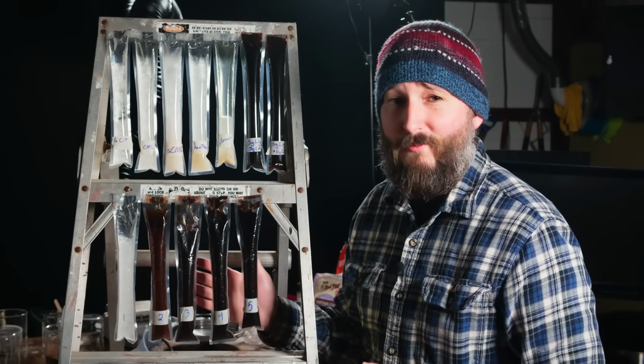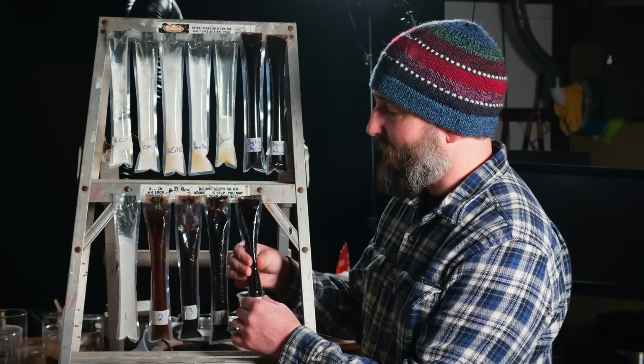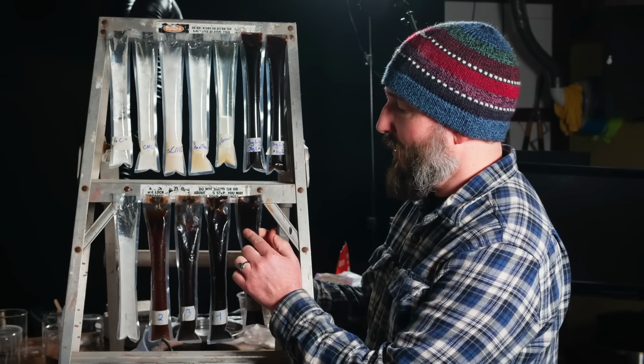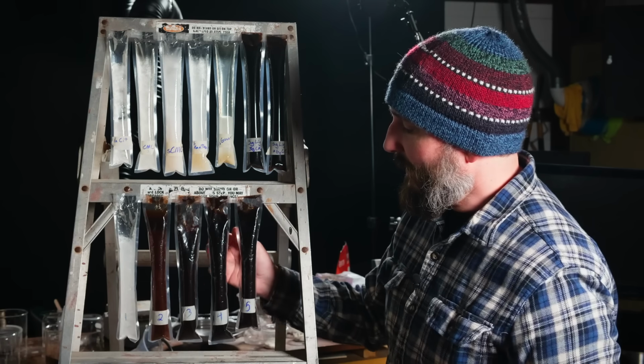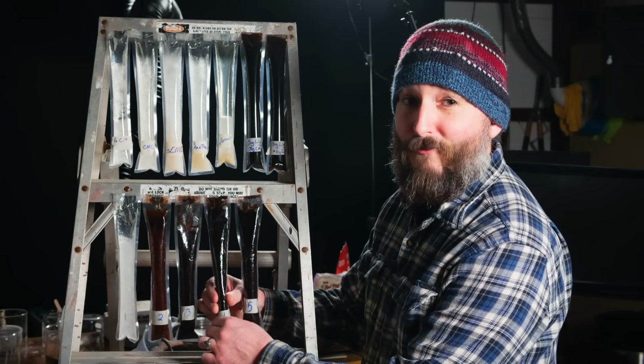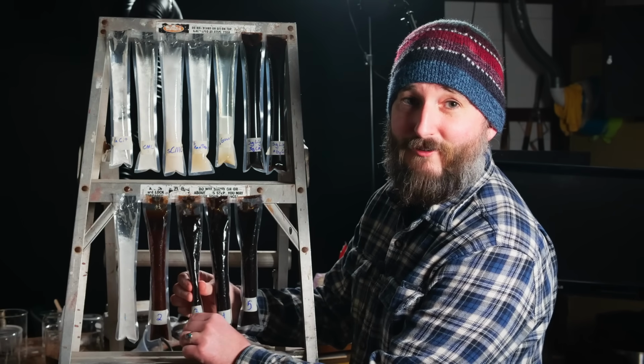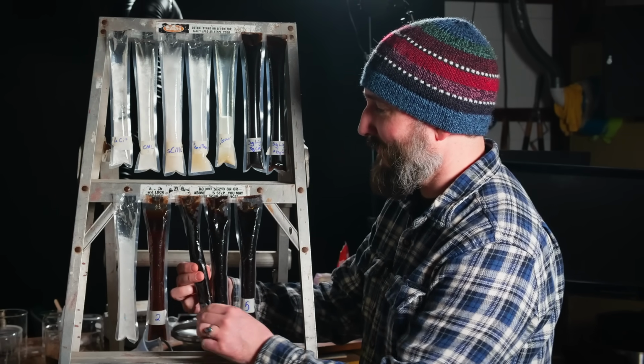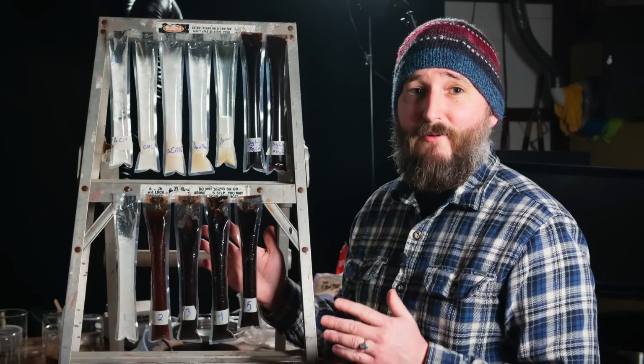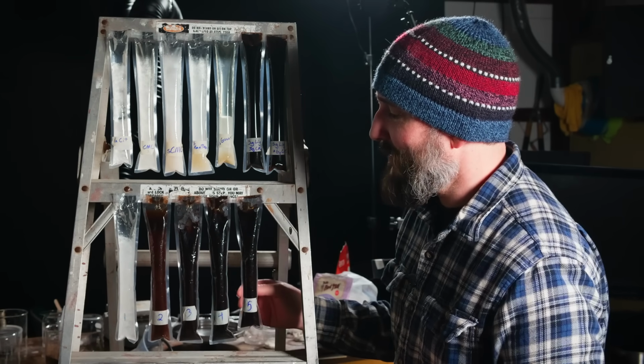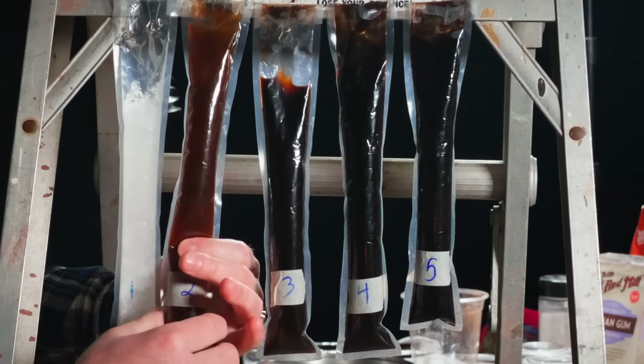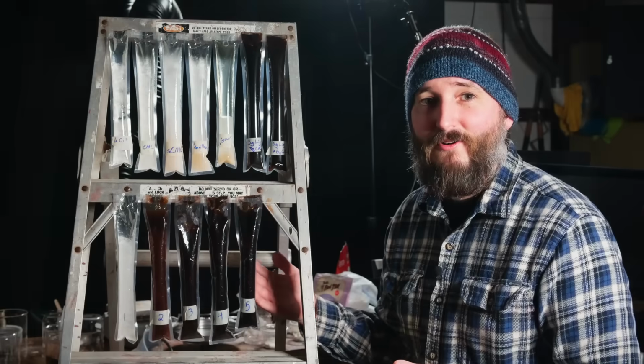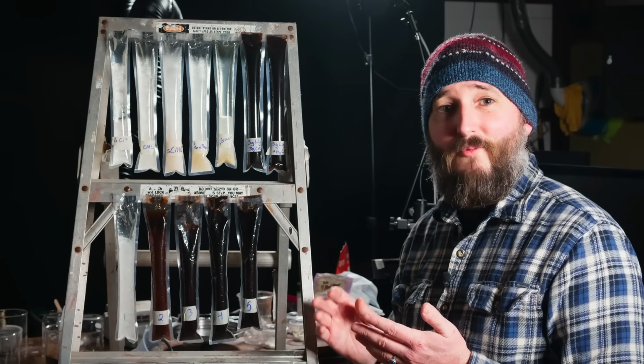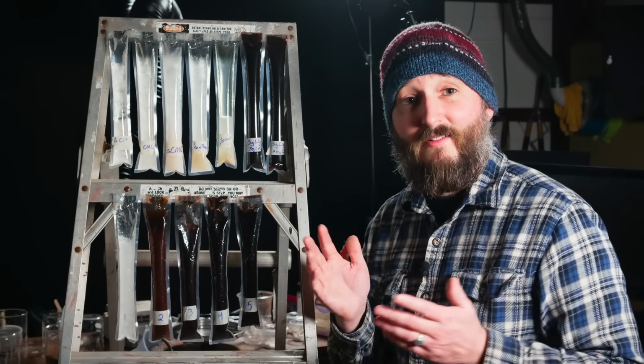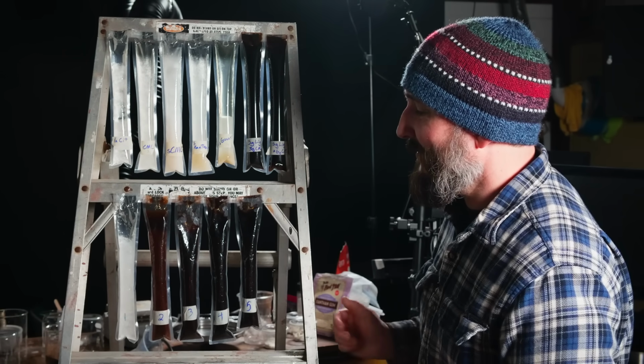3 through 5 performed pretty badly, 5 being the worst of them with the coarsest crystals and the most liquid at the top. 3 and 4 were not far behind in low performance. They just have a little bit softer crystallization in the bottom, which would make them perform slightly better in the long run, but they would still need agitation to re-homogenize the mixtures. Number 2 might have just gotten a little bit lucky at freezing early because the early triggering of a freeze cycle tends to stabilize any crystals that would form and keep them from falling out because suddenly the mixture is a lot thicker and they stay held in place.